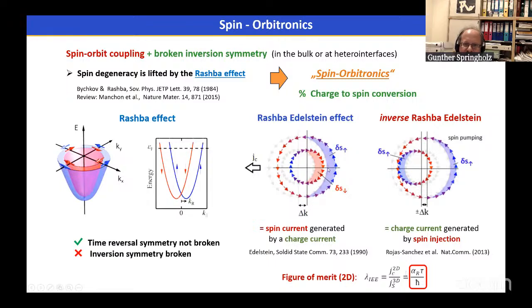And that means that this blue shaded region of electrons is populated more than the ones on the inner circle with opposite spin polarization. So that means that the current flow is imbalanced in the spin polarization. There are more electrons with spin up as compared to spin down, and that generates a spin current that is associated with the charge current.